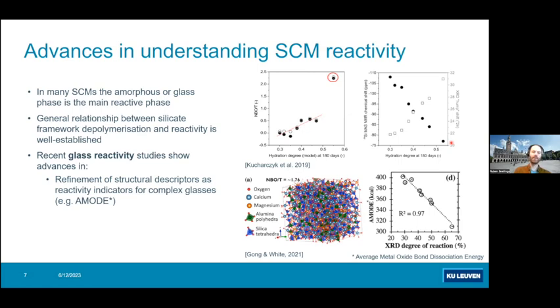However, it does more than that, and I think recent research has, for instance, shown that we can develop the structural descriptors of the glasses much more to make them more reactive. For instance, here, this average metal oxide bond dissociation energy was developed and showed a very good correlation to degree of reaction of a slag phase or an SCM phase in blended cements.